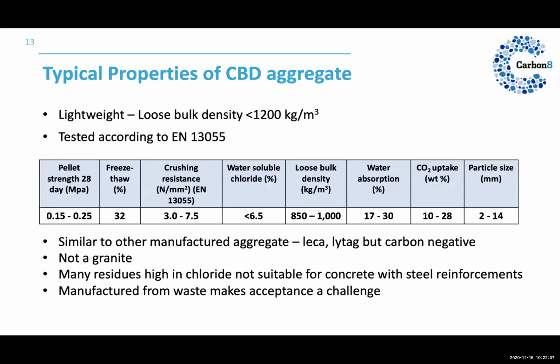So just to talk about our products, the typical properties of an aggregate made from cement bypass dusts. It's lightweight, and when you test it according to the lightweight aggregate standard 13055, you get an acceptable range of properties, typical of other manufactured aggregates such as Leca or Lytag, but of course it's carbon negative. I have to emphasize though that it's not a granite, and you've made it within 15 minutes, so it can't be compared with a strong natural aggregate, and you have to think carefully about the applications, and the application in concrete blocks is one of the most appropriate for this sort of material.